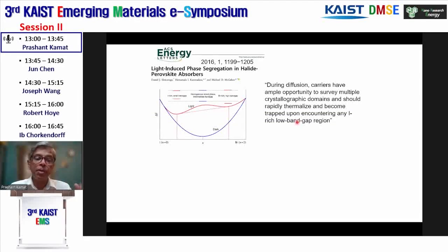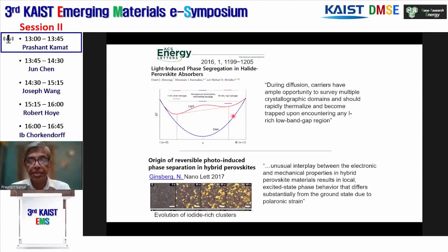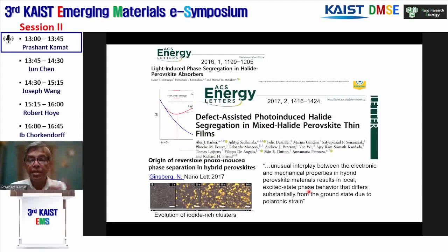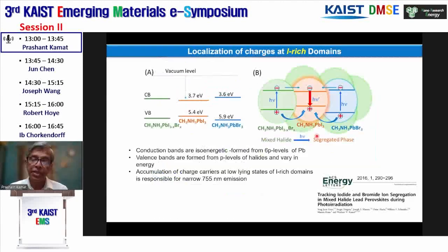So one of the things proposed early on was a two-state model. That is, in the dark, there is only one state, and there are two potential wells in the light. So that's why they get stabilized. This is a very simple explanation. There was also another explanation given, a polaronic strain model, where because of the light, the lattice gets strained and they kick out the iodide and that moves on. And then again, both theoretical predictions and our own experiments show that halide defects are very important to see this migration of ions. So this is a defect-assisted halide segregation. It was proposed because you need those vacancies to make these ions move quite effectively.